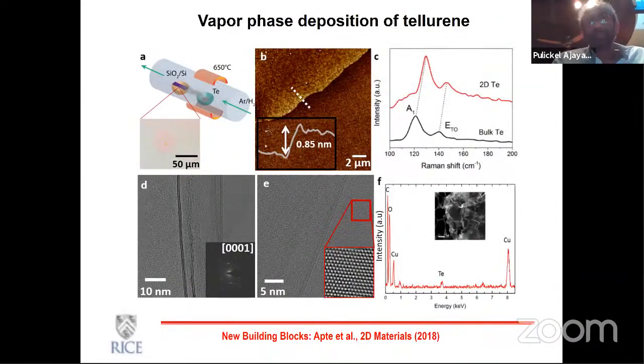The final technique that we normally use in our lab is vapor phase deposition, and this has been the most common technique to grow large area, scalable structures. And I'll show you a couple of instances. This one particularly was a recent study where we were able to deposit super thin layers of tellurium. Tellurium is an interesting material, and even materials like sulfur and selenium all follow this pattern. It forms in various types of structures, and it has different unit cells depending on what kind of phase you form these in. We were able to create really almost atomically thin layers of tellurium and explore the properties.